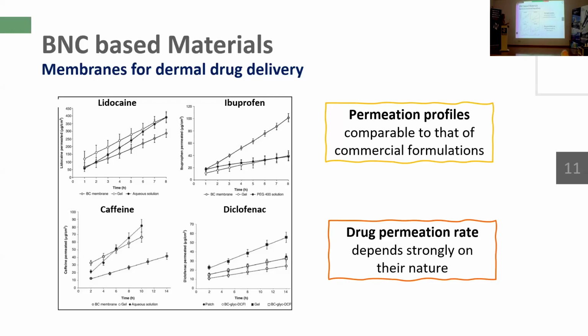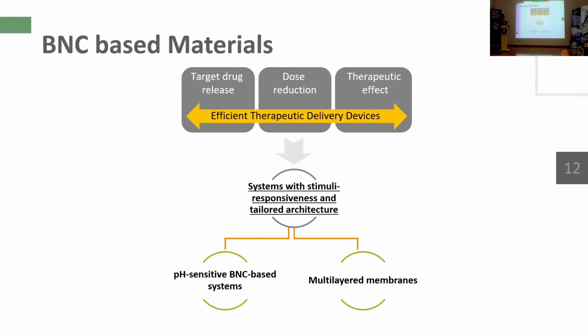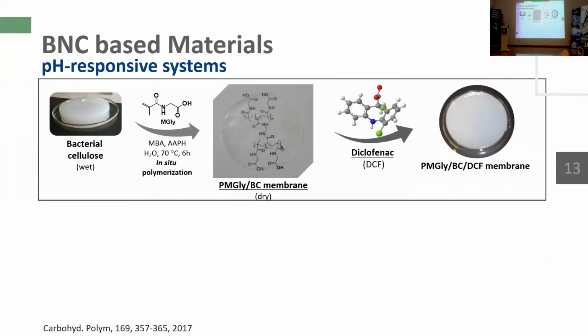So if we want to go into a targeted release or even a more controlled release, we need to go through more complex systems. In particular, we have been investigating pH-sensitive systems and multi-layered patches to try to achieve these objectives. In this work, we prepared a pH-sensitive membrane by the in situ polymerization of a monomer inside the membrane. So in this case, we incorporate the monomer, we polymerize it, and then we obtain a nanocomposite, as we can see here.